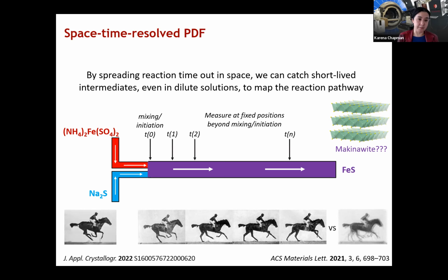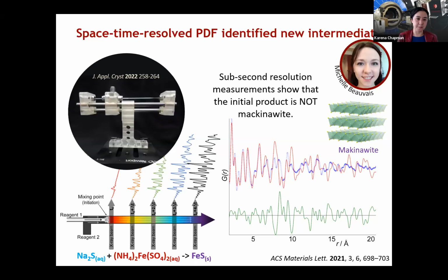So we did this type of reaction. My student Michelle developed a reactor where she mixed the two reagents together and allowed the reacting solution to continue flowing along the capillary, taking data suitable for PDF analysis at multiple points along that flow path—maybe 5 data points in the first second—then accumulating data there for several minutes. She was able to get a PDF of this first intermediate, which turns out to look nothing like mackinawite.